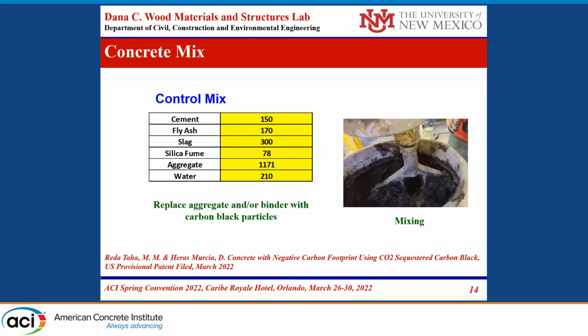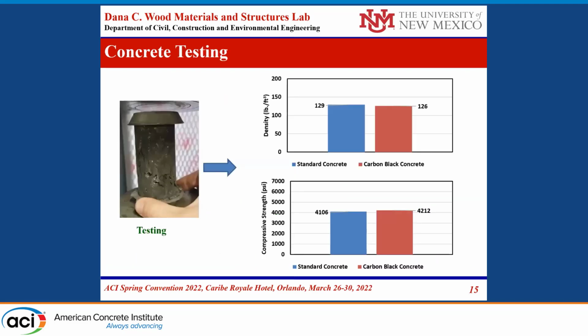And our idea was to replace the aggregate with the carbon black. So this is the testing of both the density and the compressive strength with mixes including up to 30% carbon black. And you can see there is almost no difference in either the density or the compressive strength. Again, a lot of this testing is preliminary, but we do not see any reduction in the compressive strength in the carbon black mixes. What we did here was replace the aggregates.